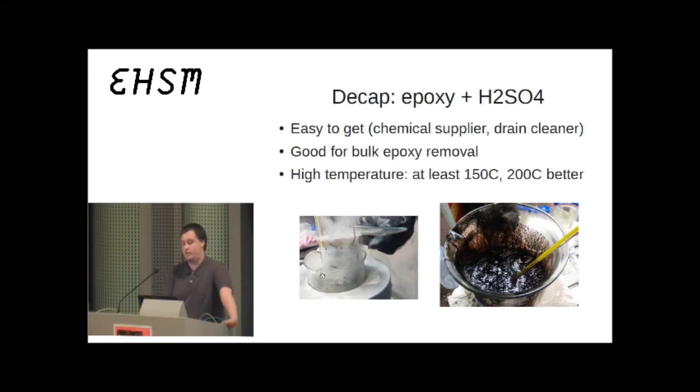And you can see, for example, I don't know how clear this is, but it produces some very heavy corrosive vapors. You can mitigate this a lot by covering it while you're working with it or refluxing it. But a lot of times you kind of want to check on it. So for example, right here, I have a Teflon beaker, which I've drilled some holes in the side and put a Teflon wire through. And so I can put a chip in there, dunk it in the acid, let it stew for a little bit, and check it out.